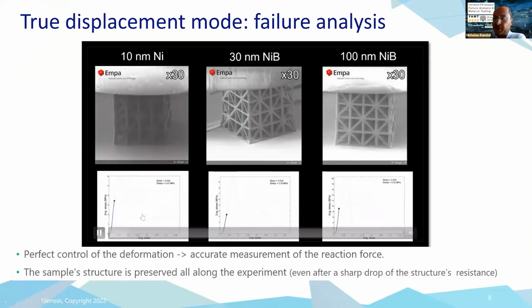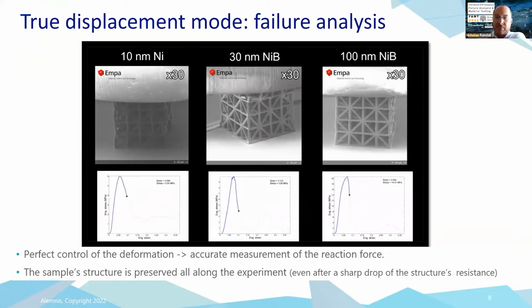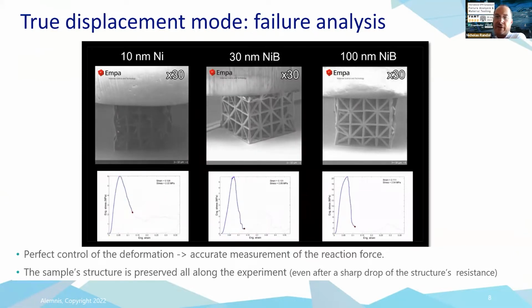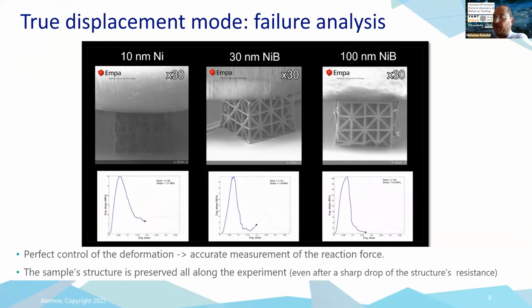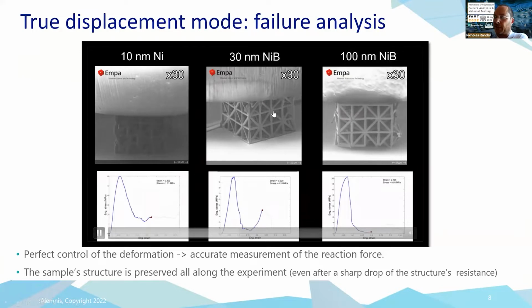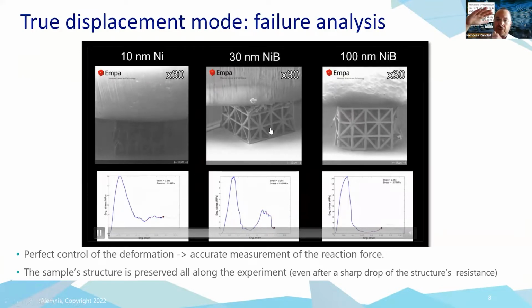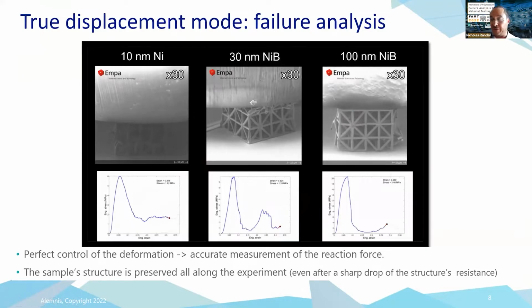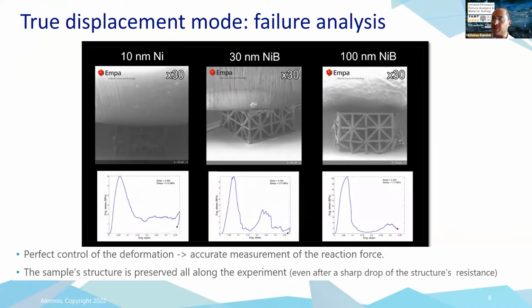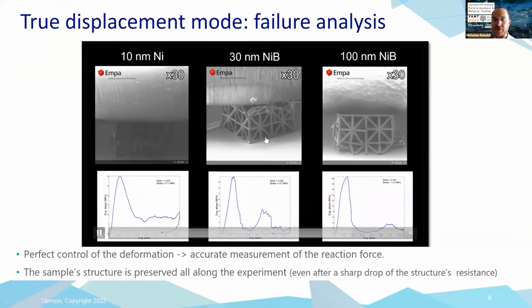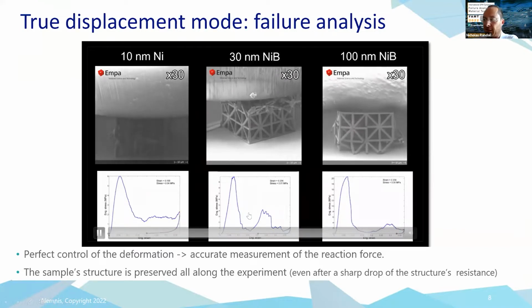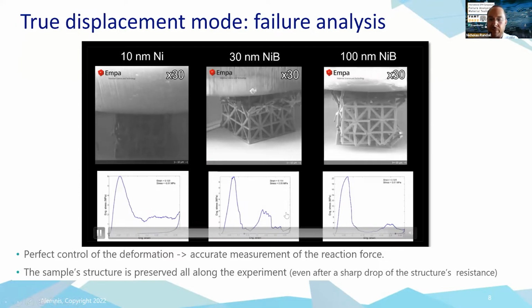One important point, different to most nano indenters, is that this system is a displacement controlled machine. This is very important for deforming large structures. You can see here, this is a 3D printed structure. If this was a load controlled experiment, as soon as we start to crush, we're going to suddenly crush very fast and not get any data. So it's very important to have displacement control in order to have constant speed and therefore the entire deformation history of the material.